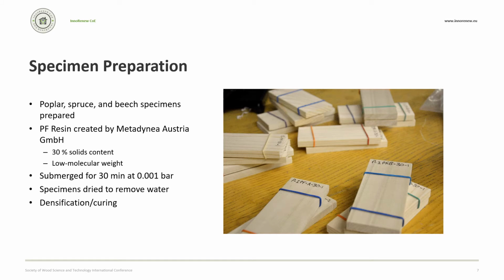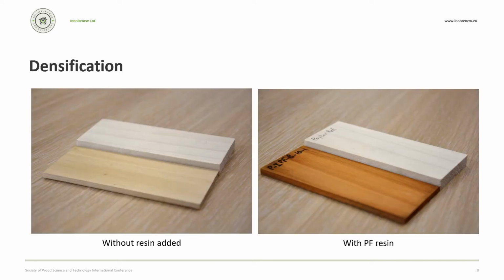We created wood specimens from poplar, spruce, and beech. We then impregnated the samples with a phenol-based resin created by Metadynea Austria GmbH. After the vacuum impregnation, water was removed from the samples by drying them, but taking care not to cure the resin solids within the wood. We then densified the specimens.